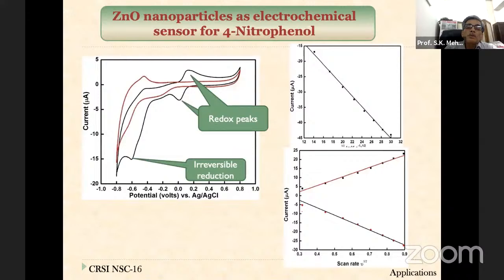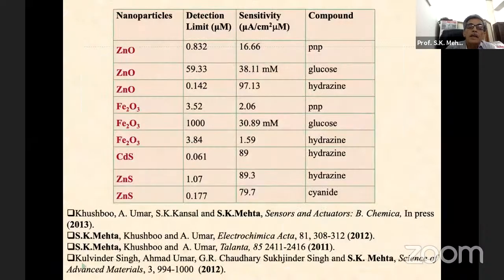Similarly, zinc oxide we used for creating sensors for 4-nitrophenol, and there again a similar procedure we applied, and I can show the table there. We had this zinc oxide, iron oxide, cadmium sulfide, zinc sulfide, all such particles were created, and we found the detection limit and the sensitivity and the compounds for which they were used.